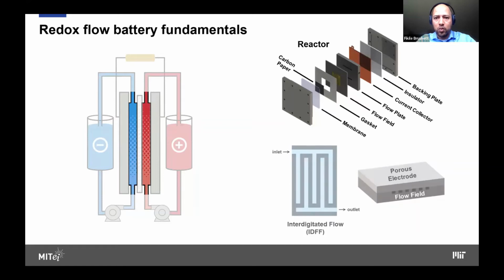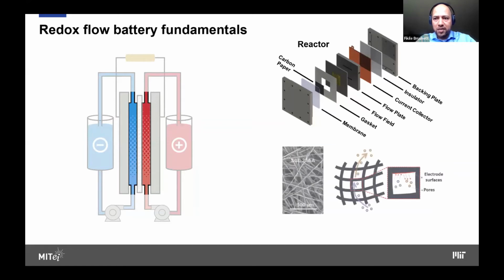And this forced convection through these porous electrodes, which are things like carbon paper, leads to the redox reactions that occur on the surface of the porous electrode. And then the material will move out of the reactor and move back to the tank. And so essentially you're cycling these materials around and around to charge and discharge them when you want to store energy or when you want to release energy to the grid.